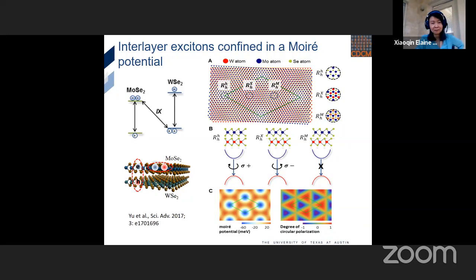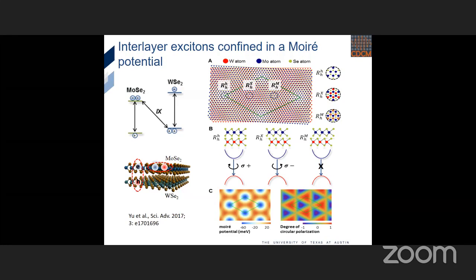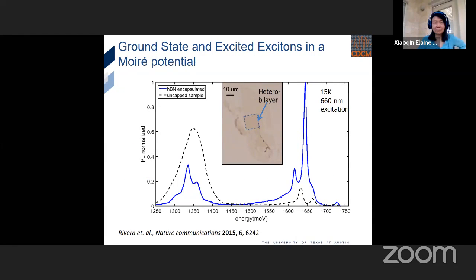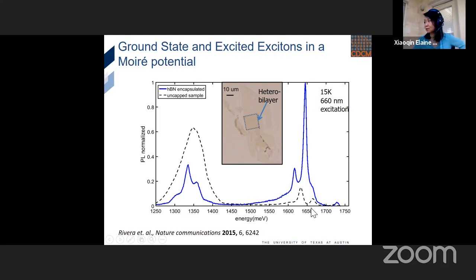Is there some experimental evidence that this heterostructure exciton is also quite bright, or is it slightly different? They're pretty bright, in the sense that in this particular case the interlayer is brighter than the intralayer because it is energetically more favorable. Other people claim that in the highest quality interface you don't have intralayer at all. Some papers say that when you have a heterostructure, the intralayer is only observable in absorption measurement, no longer in photoluminescence. So how bright are they?